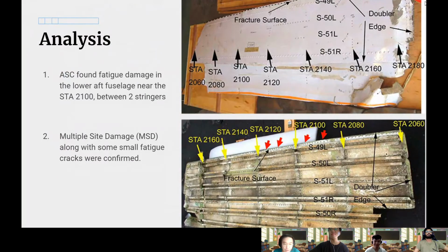Based on the recordings of the cockpit voice recorder, or the CVR, and the flight data recorder, or the FDR, radar data, the DADO panel open-close positions, the wreckage distribution, and the wreckage examinations, the ASC concluded that the in-flight breakup of the aircraft as it approached its cruising altitude was highly likely due to the structural failure of the aft lower lobe section of the fuselage. The ASC found evidence of fatigue damage in the lower aft fuselage centered about STA 2100 between stringers S48L and S49L, under the repair doubler near its edge and outside the outer row of securing rivets. Multiple site damage, or MSD, including a 15.1-inch through-thickness main fatigue crack and some small fatigue cracks were confirmed. Next slide.